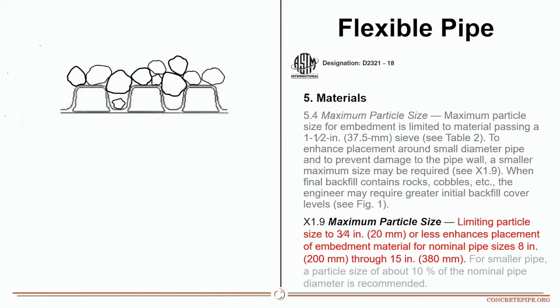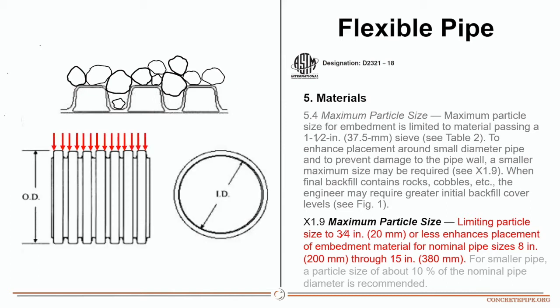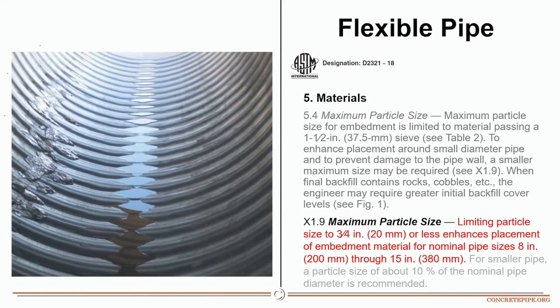The width at the bottom of the valley is 1/2 inch, and a 3/4 inch stone may block the valley before smaller particles can fill in the corrugation. When this happens, the loads will end up being concentrated loads on the ribs. Those concentrated loads will lead to long-term corrugation growth, which will increase Manning's N.